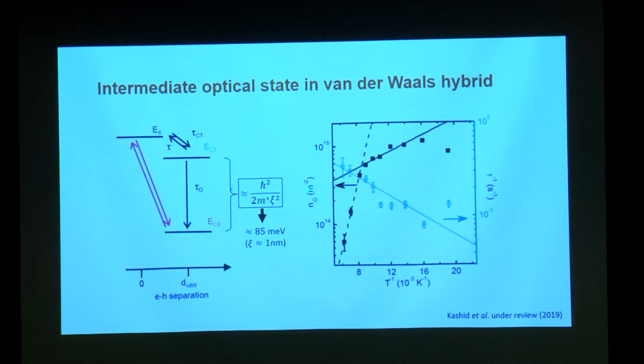As a result, the number of charge carriers in graphene decreases very fast in an activated manner with an activation energy of 85 millielectron volt, exactly the delocalization energy.